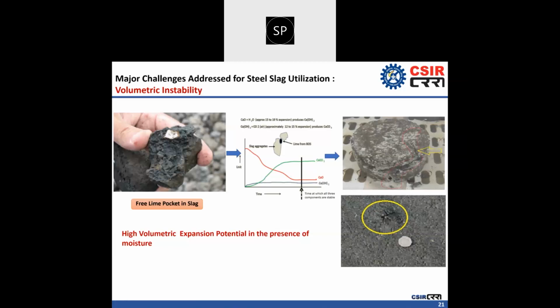So therefore, in order to make a good bituminous mix using steel slag aggregate, it is imperative to subject the steel slag aggregate to different aging treatments, and this necessary modification is carried out by different steel plants before supplying these materials to the road construction industry. In the second photograph, you can see the pop-outs that have developed in the asphalt mix when untreated steel slag aggregate is utilized for construction work. It is due to the volumetric expansion in the slag aggregate.